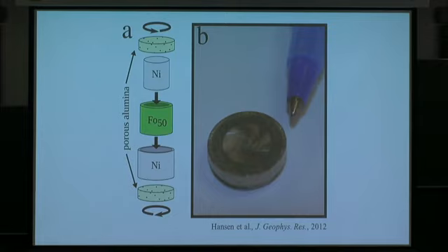And you'll probably notice that this says FO50, and so I should point out that a lot of what I'll show comes from samples where we've doped them with additional iron. So we've made a very iron-rich olivine. And the first order benefit of that is that it speeds up the kinetics. And so you can get a lot more done in the short time that you can operate the instrument. So we want to go to really large deformations. We like to be able to get to really high strain rates.